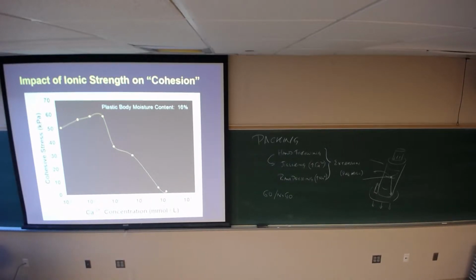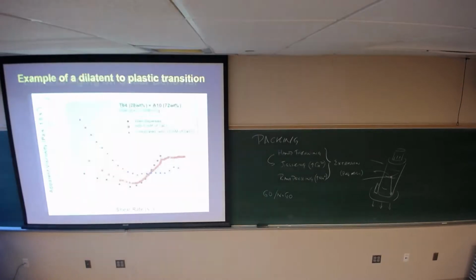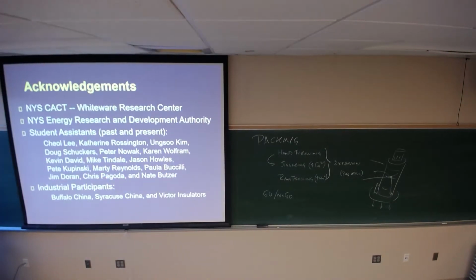So to reduce the plasticity or to make the body softer, that's the problem. In fact, you would say to increase the plasticity, not to reduce it, but to reduce cohesion, okay, you would add salt, specifically calcium. You can do it with sodium, but we're going to use calcium. So increase in the calcium ion concentration makes the clay softer, and it makes it easier to form in something like jiggering. Okay, so we did all of this, and